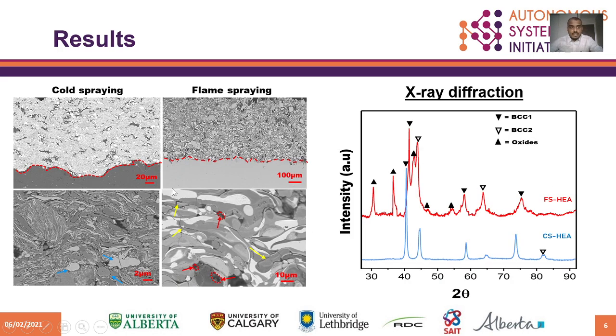Here are the results. The scanning electron microscope shows that the cold spray exhibited a significantly plastically deformed surface with the absence of cracks and pores, whereas the flame spray shows numerous cracks and pores, where the porosity is about 1.7 volume percentage, and the average coating thickness is around 421 micrometers. The X-ray diffraction study suggests that both the coatings exhibited BCC phases.